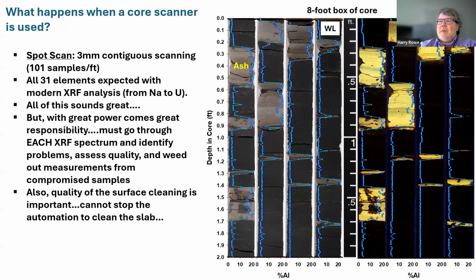So if it gets to a point where it's going through a salty interval, there's no way to just stop it, clean up the rock, and then tell it to keep going. There's no way to make it go back and redo this without redoing the entire box. So be very careful when you do core scanner studies. Ask for the raw data and ask for a demonstration that the chlorine and the sodium are very, very low and it's not impacting the surface scans.